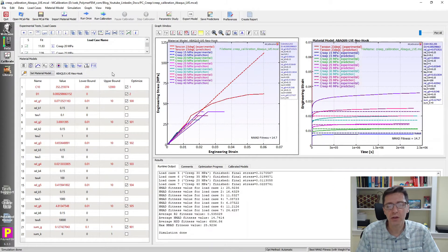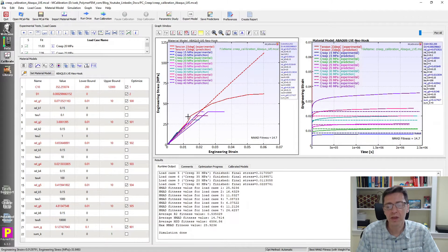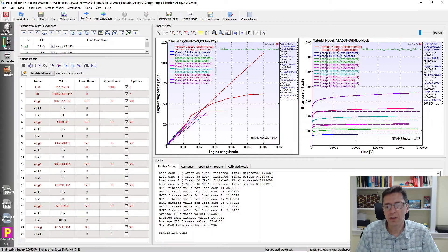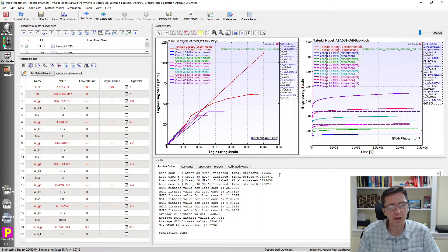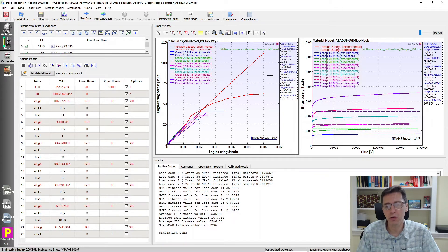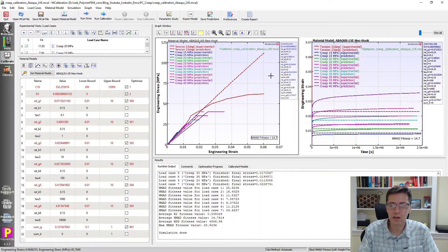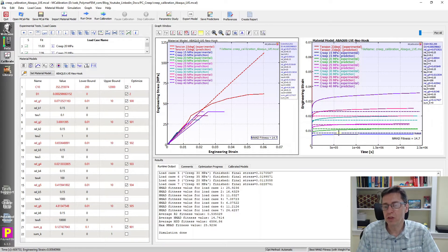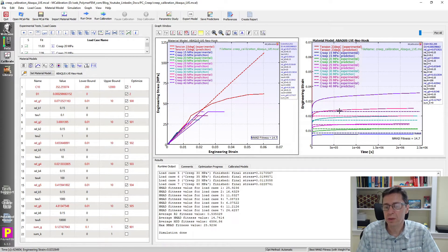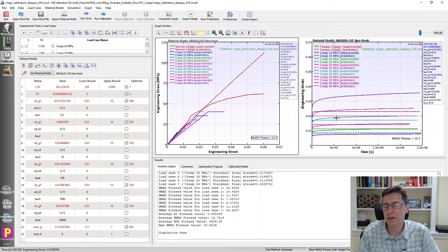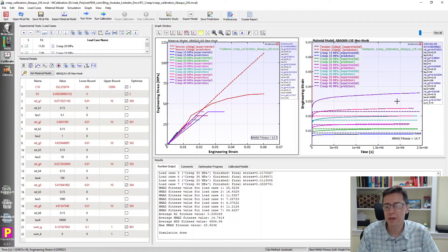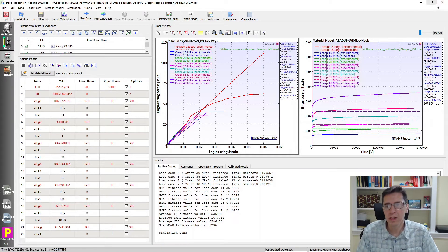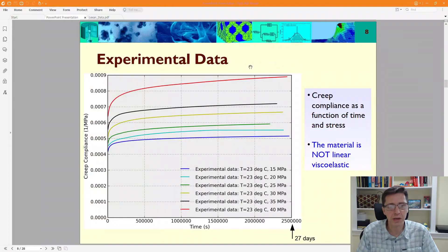If I run it once now, the predictions look like this. The predictions are not very good. The average error is 14.7%, which by itself is not so bad perhaps. We see that the monotonic curve goes straight up, not rolling over like it does experimentally. The shape of these curves is not right. It's really not the choice of material that you probably want to use in a case like this. We can do better.